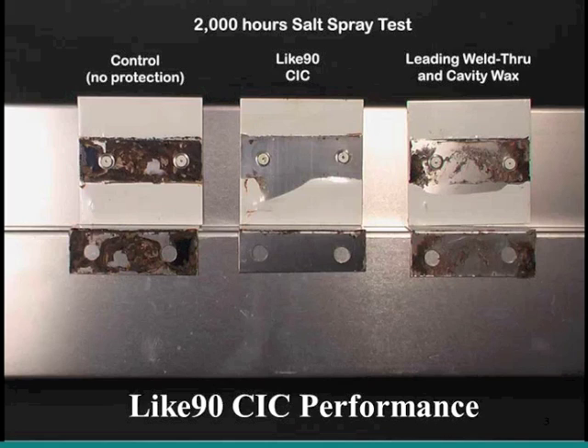Now, some of the unique benefits of this product are the fact that your typical weld-through primers that are out there, you got your zincs and your coppers, and anybody who knows welding can identify those. When you go to weld through them, you get a lot of popping and splatter coming back. This technology has no metals in it. So with no metals in there, you don't have any sacrificial metal that you're trying to burn through. You don't have pigments in it. So when you go to weld through it, you get a clean weld all the way through, and you also get no porosity in the weld.